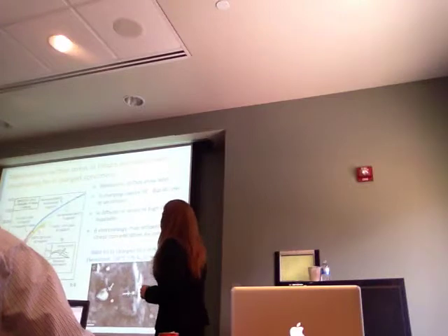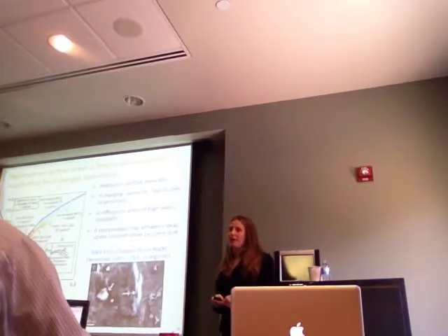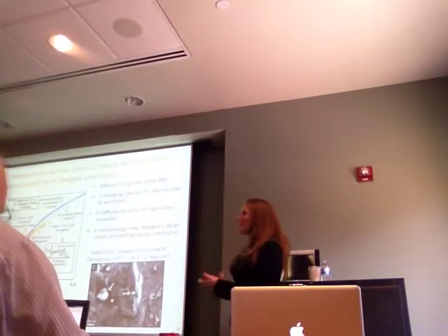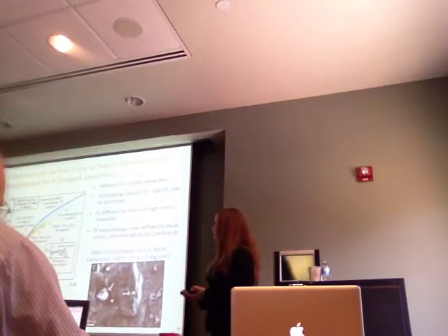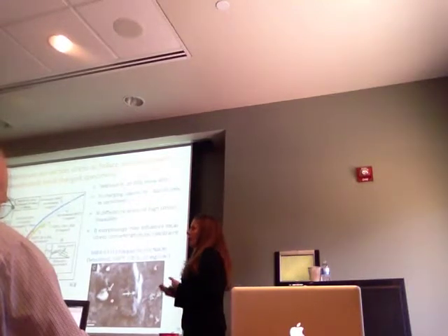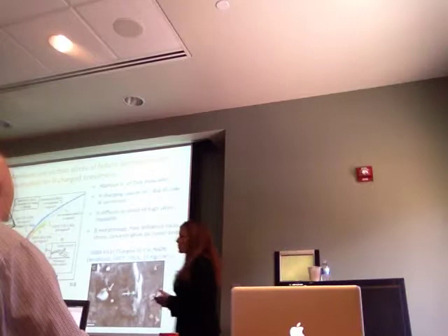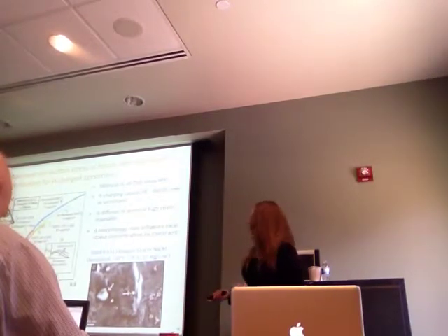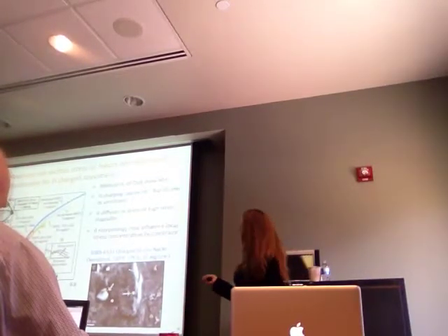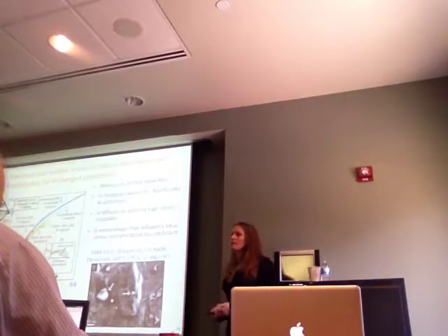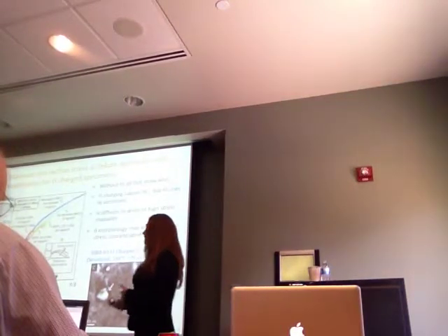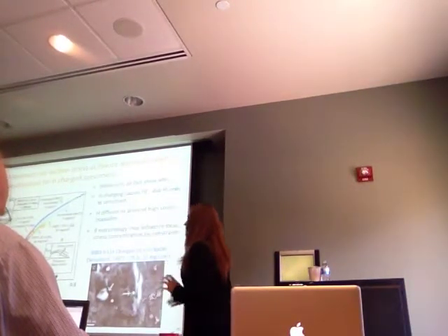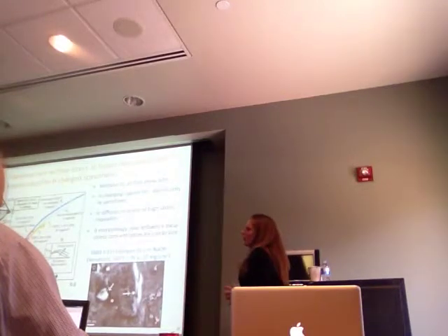This technique could also be used to characterize beta on the grain boundaries. So since we had these intergranular embrittlements, and it wasn't in a dissolving electrolyte, we still have beta on the grain boundaries when we open these up. So you could be able to see the particles, measure the size, measure the spacing. This technique has a few challenges left to work out, so we did not focus on this in this work.